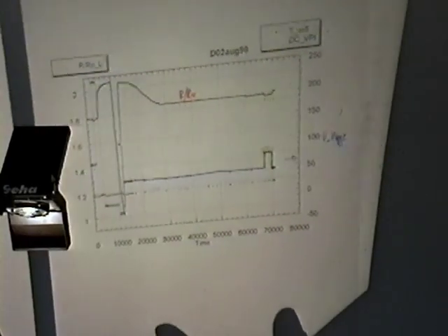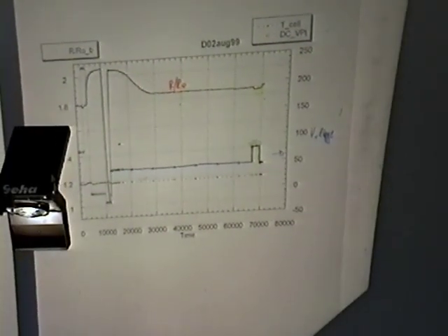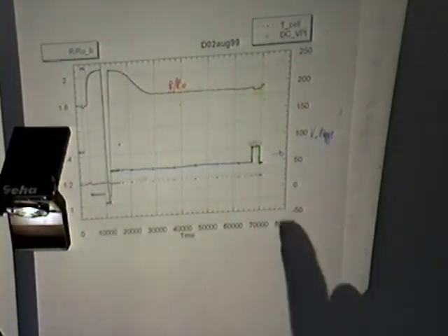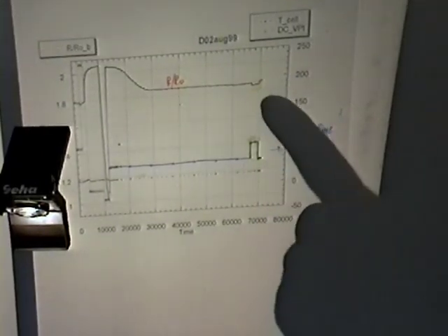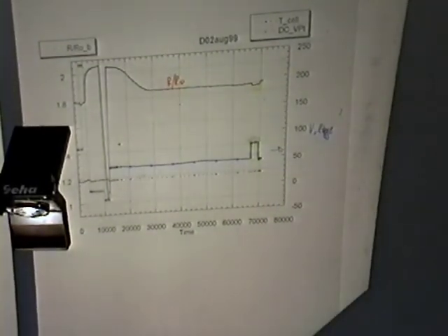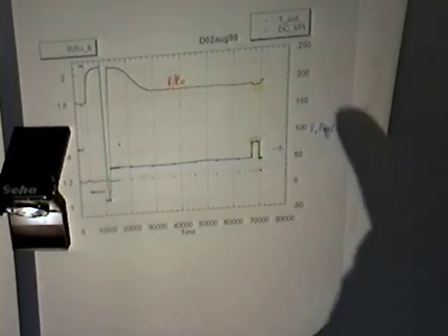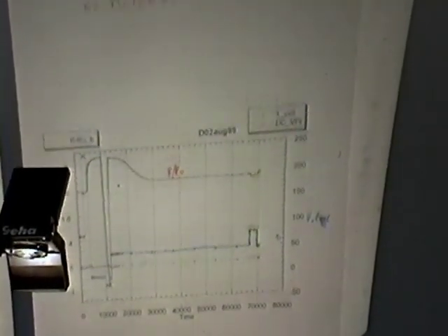We took some conventional procedure, meaning loading, deloading, and so on. We found resistance ratio 1.82. We increased the current, the loading increased a little bit. Increasing the current further, the loading fell again. So nothing to do.